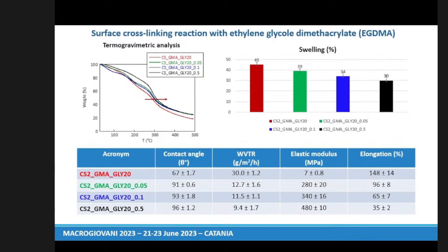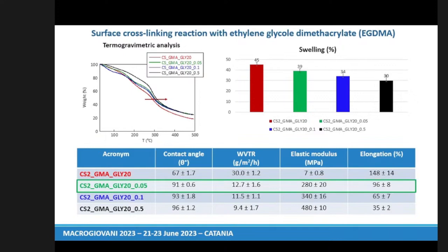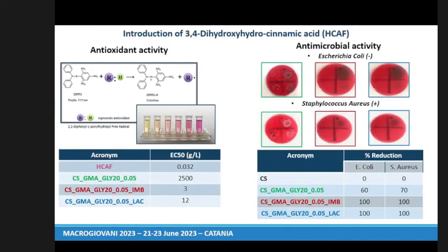What is more important to see is that only in the case of the lowest concentration of EGDMA, we obtain the best elongation percentage. For this reason, we evaluate the introduction of our antioxidant only on this matrix. The evaluation was done by measuring antioxidant activity against a model radical named DPPH. And we can see that in both strategies of introduction, we have an incredible decrease in the value of EC50.